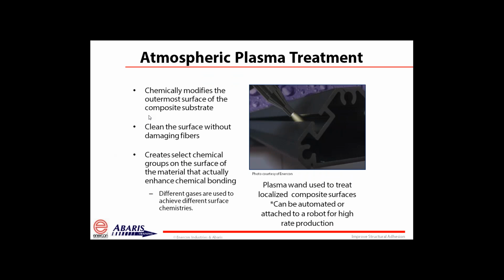But the good thing about plasma treatment is that not only are you modifying the surface, you're changing the microtopography of the surface or the surface area, but you're also able to clean the surface without damaging the fibers. This creates select chemical groups on the surface of the material that actually enhance chemical bonding. And it can be adjusted using different gases to achieve exactly the relationship you want between the substrate material and the adhesive that you choose to use for bonding the substrates together.